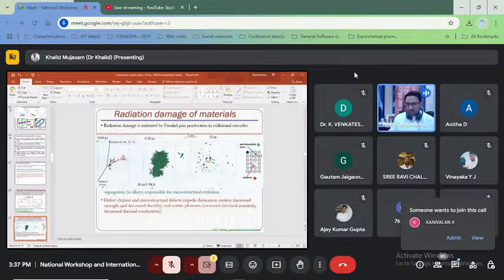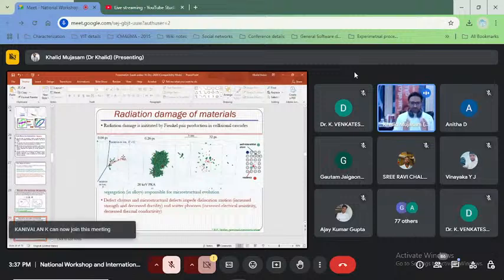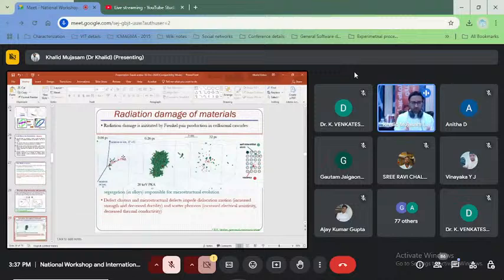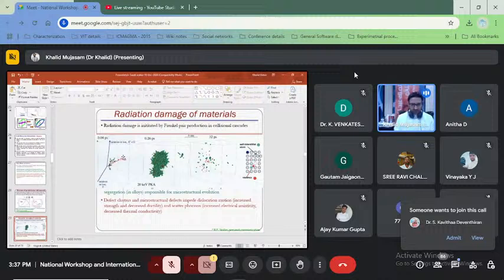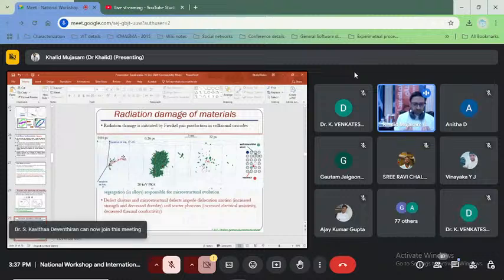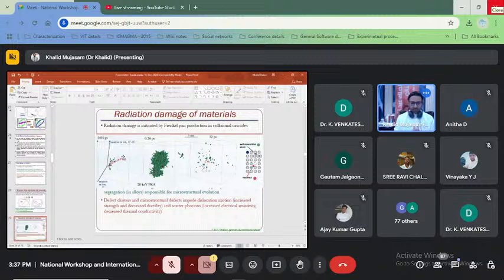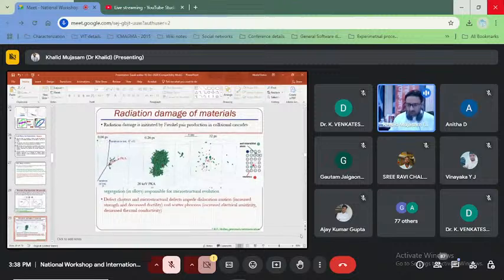Here you can see that the damage is controlled in several ways. First, the flux: how much flux is irradiated on your substrate. Second, the time of exposure: how long your material is exposed. Third, what type of radiation you have chosen for the particular damage. And fourth, the energy of your beam, how much you accelerate: 100 MeV, 150 MeV, 50 MeV, or 200 MeV. What sort of beam you require.